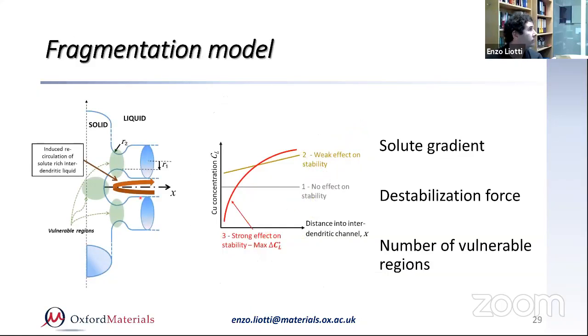And for the explanation, we look at this kind of mechanism. You need three fundamental key aspects to fragment a dendritic array. The first one is that you need a solute gradient. If you are in an interdendritic channel, and this is a schematic of a primary and secondary arm, you've got some vulnerable regions, which are regions of high curvature, which are essentially the neck of the secondary dendrite where they are attached, and also primary thinner areas. And also you've got a solute gradient in the channel.